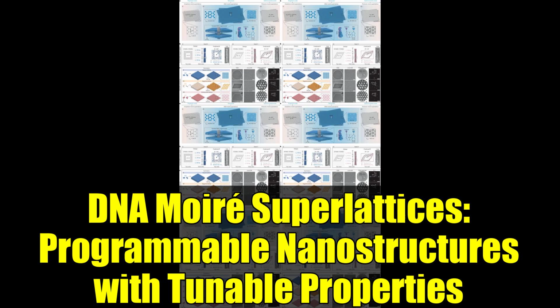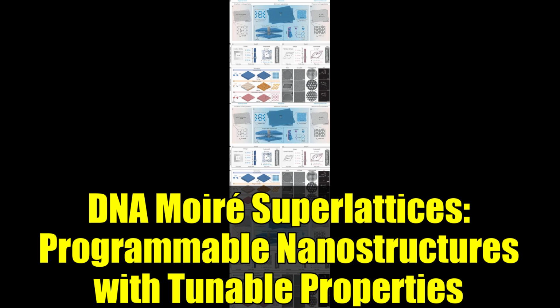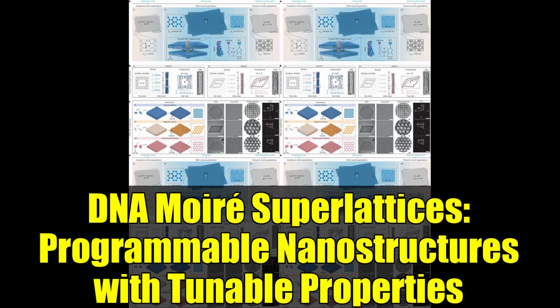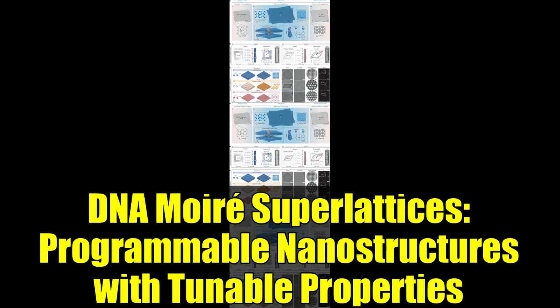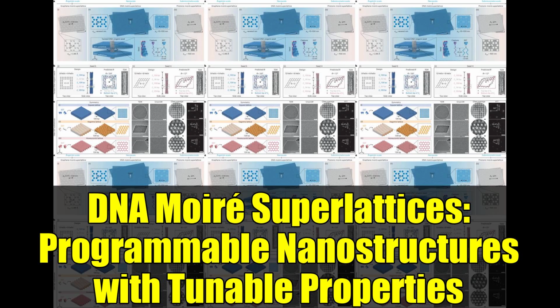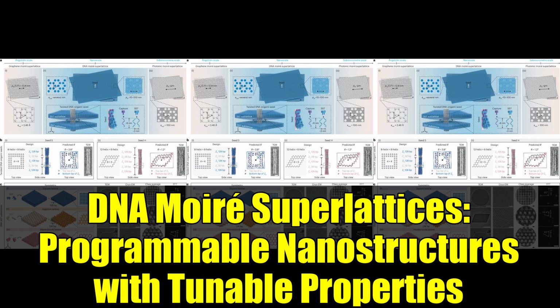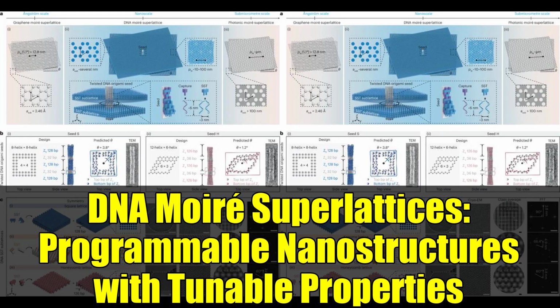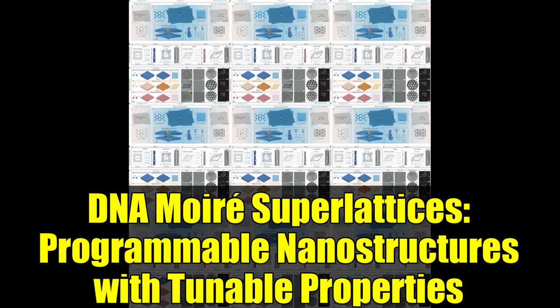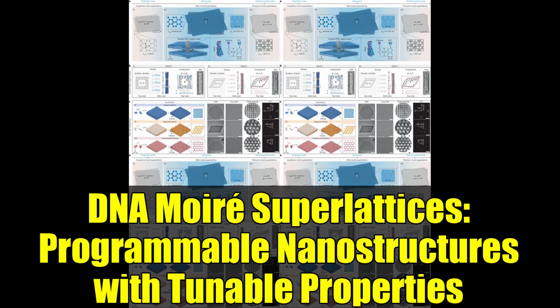It turns out that seed design and nucleation pathways are everything. In unseeded DNA assembly, new lattices grow slowly, as individual DNA tiles randomly bind and nucleate. Seeding, on the other hand, accelerates and directs the assembly dramatically, but only if the seed presents the correct pattern of capture sites. These captures act as molecular glue for two neighboring domains on a DNA tile, and their arrangement, fully paired, partially paired, or alone, switches the system into fully cooperative, partially cooperative, or non-cooperative nucleation regimes.